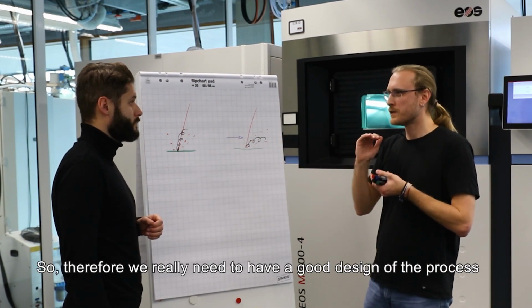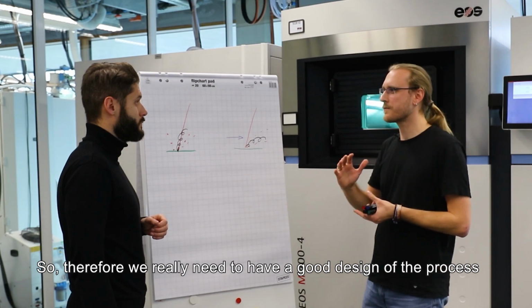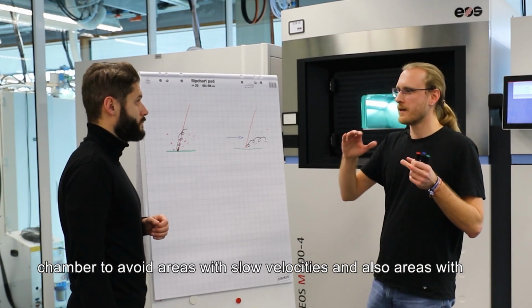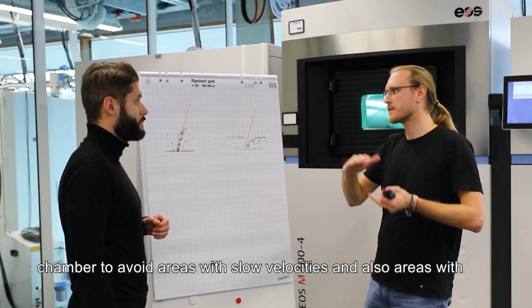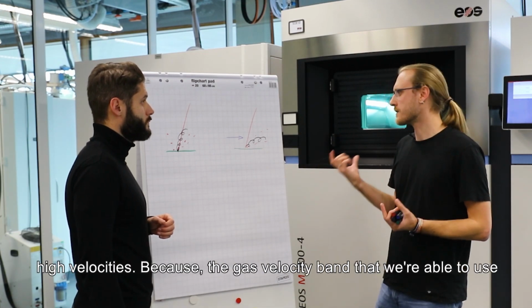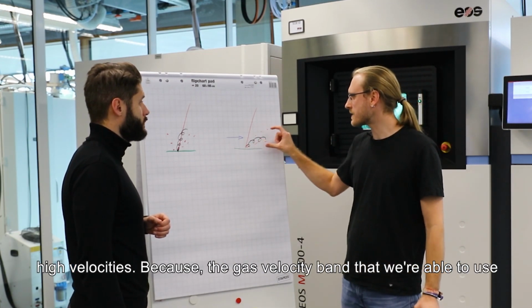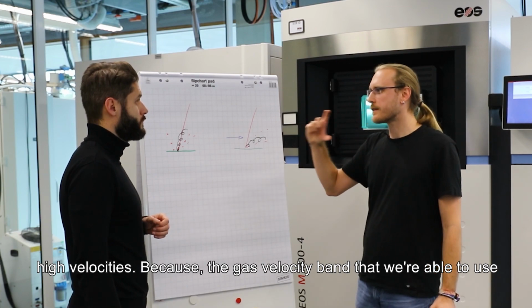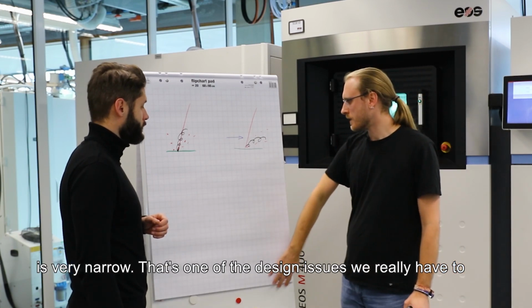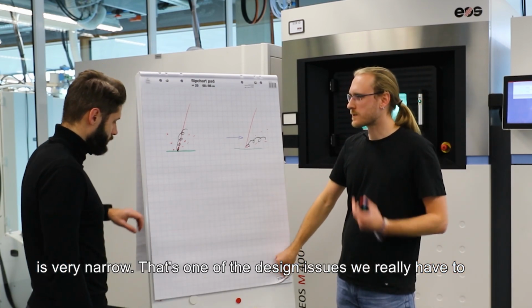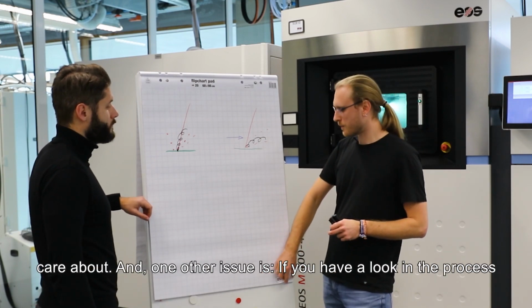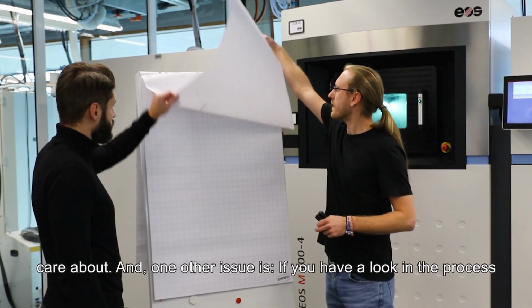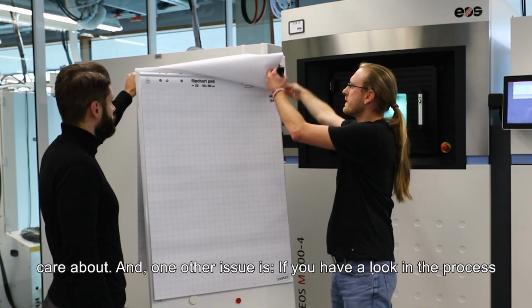So therefore we really need to have a good design of the process chamber to avoid areas with low velocities, and also to avoid areas with high velocities, because the gas velocity band that we're able to use is very narrow. And so that's one of the design issues that we really have to care about. And one other issue is,